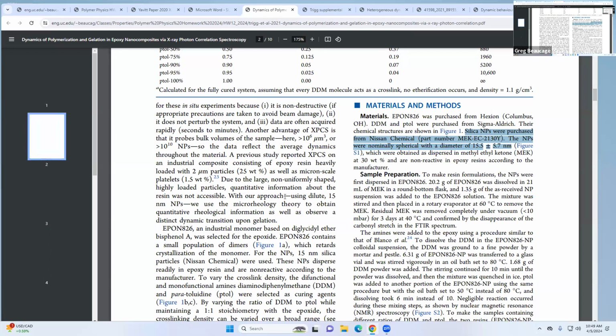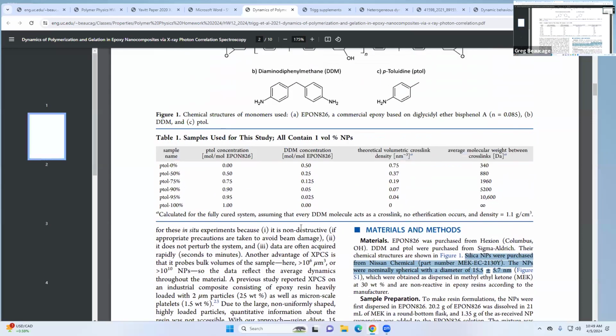And that's probably why we saw those collective dynamics. We weren't at the length scale where diffusion is important. And the other thing that they did here was they only added in 1 volume% of these fillers. Very small amount, right? So if you imagine looking at the nanoscale, I've got basically a silica particle isolated on its own. That should be a nice environment for diffusive dynamics.